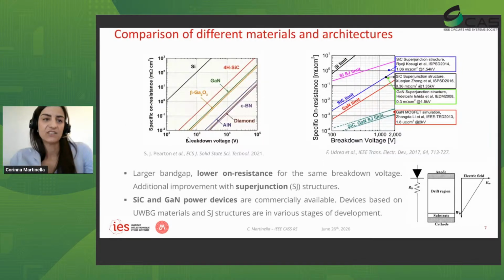This material is particularly interesting for power electronics for the following reasons. When we look into power devices, we want to maximize a specific figure of merit. We want to have devices that can work at very high breakdown voltage, so sustain a very high electric field, but also we want to reduce the specific on-state resistance. So we see that this is where silicon devices are placed on this graph. And we can improve this figure of merit following 2 directions. The first is by changing the material. You can see how wide bandgap materials such as silicon carbide and gallium nitride improve this figure of merit. And things get even more interesting with ultra wide bandgap materials such as gallium oxide or diamond.